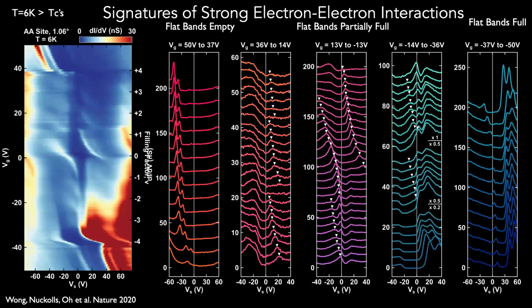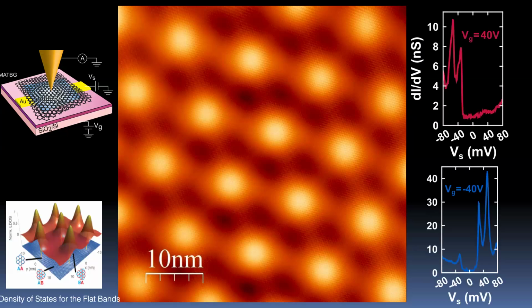Okay, so it's a busy slide, but let me walk you through it. Let me go back once. So you can do spectroscopy. Remember, in STM, you measure the tunneling density of states, the dI/dV, as a function of sample bias. And there is a gate here, so you can adjust your gate to fully occupy the flat bands or completely empty them. And these two sharp peaks are the Van Hove singularities of these flat bands. From the width, you can see that they are about 10 or so milli electron volts. This is very sensitive to the strain in the device. But you see that they're sharp.